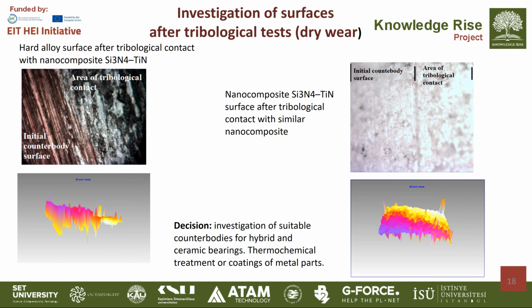In conclusion, the comparison clearly demonstrates that ceramic contact provides much better tribological performance than metal ceramic contact under dry wear condition. The silicon nitride nanocomposite shows remarkable resistance to wear and maintains surface integrity, making it a strong candidate for bearing and sliding components in the extreme environment.